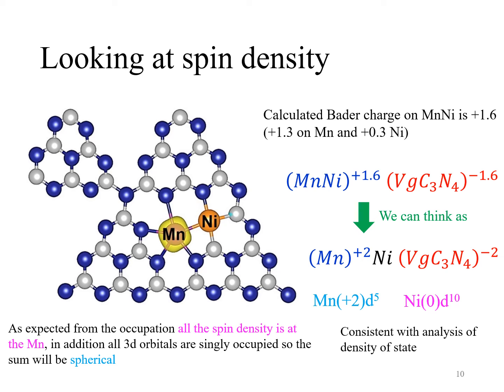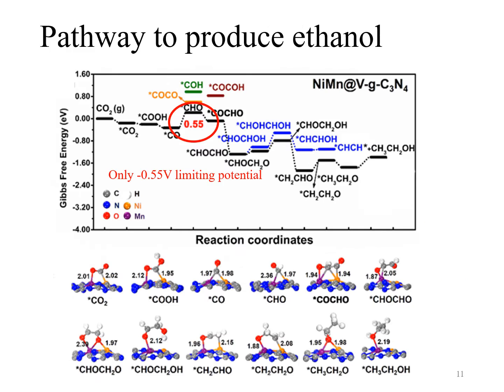So how does this electronic state help us? Here we are looking at the reaction process of CO2 to form ethanol. And here you can see the schematic geometries. The key point is we only need -0.55 volt limiting potential to form this ethanol. And the important reaction for the CC coupling is between CHO and CO, making this CO-CHO reaction intermediate.